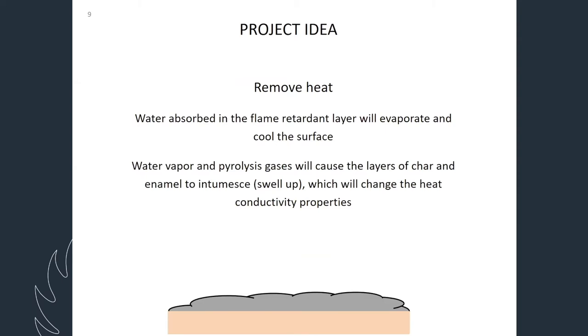We can also remove the heat. There will be some water absorbed in this flame retardant layer that will evaporate and cool the surface. When the water vapor and pyrolysis gases form, they will blow up this char layer and enamel, so it will intumesce and swell up. And this can change the heat conductivity properties.